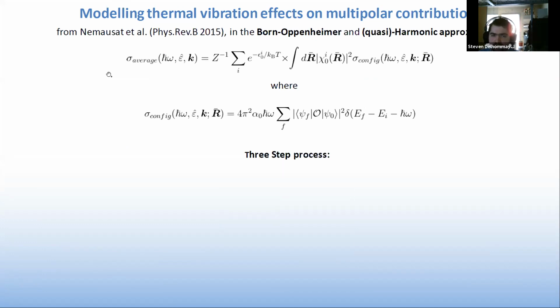We used the calculation protocol that is described and developed in Nemausat et al. from 2015. And it is placed in a Born-Oppenheimer and quasi-harmonic approximation framework. And so basically, we use this big, scary expression. Actually, scary depends if you like formulas or not, but still it's quite big. But the simple meaning of this is that we can calculate a spectrum that includes all the thermal vibration effects as an average of a number of single spectra, all calculated for out of equilibrium configurations of the material. And so here we have just the out of equilibrium spectrum for one of those configurations.